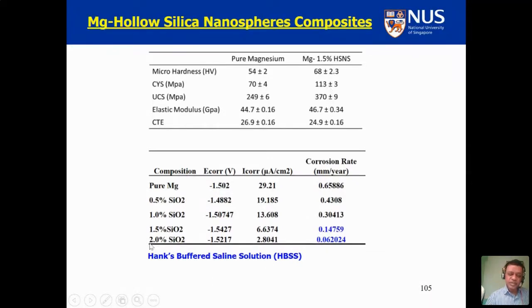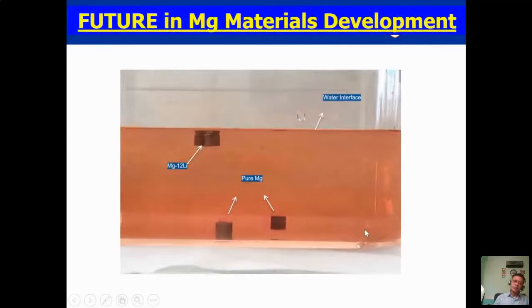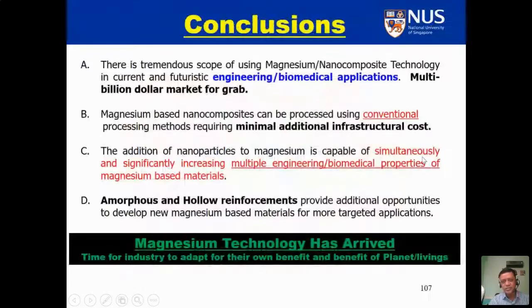And for 2% SiO2, your corrosion rate is also very, very low in the physiological medium, which is Hank's buffered saline solution. So we are also trying to develop materials which are even lighter by very judiciously using the alloying element. What you see here, this piece of pure magnesium, is settled here, so it sinks in the water. But if you use a proper alloying element, you can make it float on the water. It is still below the water surface. We want to take it above the water surface like a ship. So that is the future direction we are focusing on.